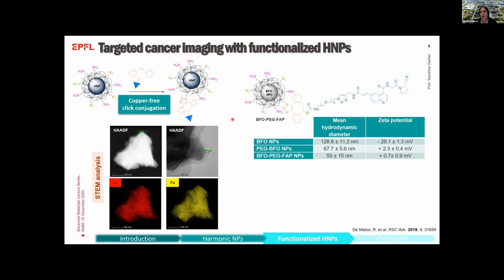Here you have an example of the conjugation performed using the specific inhibitor of fibroblast activation protein alpha. We followed and monitored the different steps of the functionalization by measuring the mean hydrodynamic diameter of those nanoparticles and their zeta potential. The values are consistent with first the introduction of amino groups at the surface of the nanoparticle, so we go from a negatively charged surface to a positively charged surface. Then we have the introduction of the ligand, which does not affect the zeta potential of the nanoparticles.